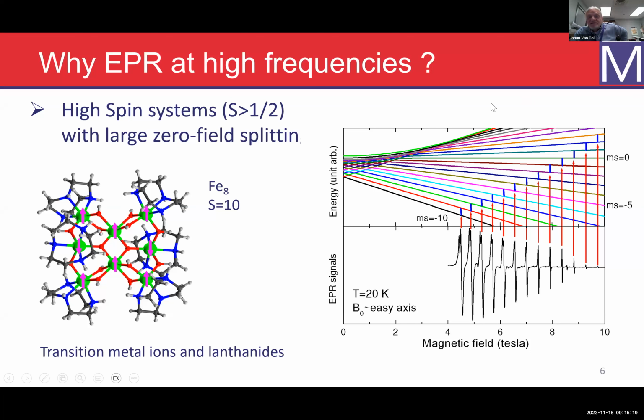Yeah. Of course these are really small splittings. I actually wanted to put in an example that I didn't put in, but if you, for example, look at amino acid radicals, you do mutation of a nearby amino acid near your reaction center or your active site. You can actually see small changes in the G-tensor as a function of your substitutions. So it tells you also a little bit of how the environment changes by doing different substitutions of amino acids in the biological system, for example. So in that sense, it depends on geometry, I guess, and how much coupling you have with the surroundings. I hope that answers your question.